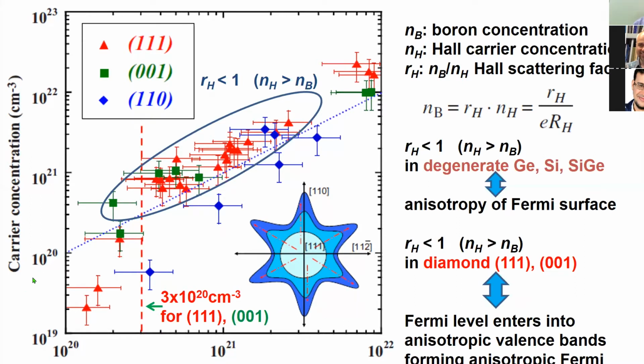This dotted line represents 1-to-1, so this is 10 to the 21st, and this is 10 to the 21st per cubic centimeter. This line corresponds to the carrier concentration being the same as the boron concentration - this is the acceptor boron. So these lines should be here, but what we measured is a little bit higher.